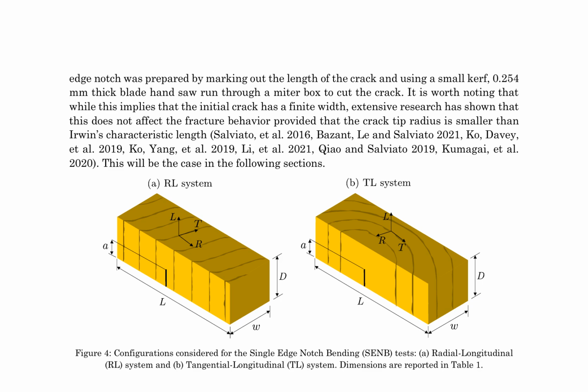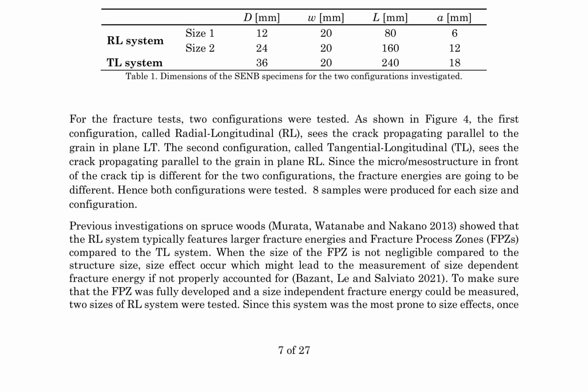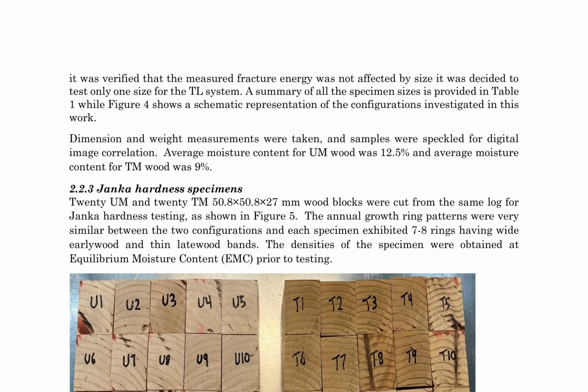The SENB specimens were prepared with dimensions as outlined in Table 1, featuring a 0.254 mm wide edge notch cut using a hand saw. The RL system exhibited larger fracture energies and fracture process zones, FPZs, compared to the TL system, necessitating the testing of two sizes for the RL system to ensure size-independent fracture energy measurements. Conversely, only one size was tested for the TL system due to its reduced susceptibility to size effects. The wood blocks for Janka hardness testing were cut from the same log, displaying similar annual growth ring patterns and densities at equilibrium moisture content, EMC.